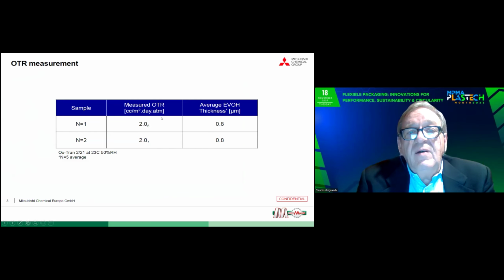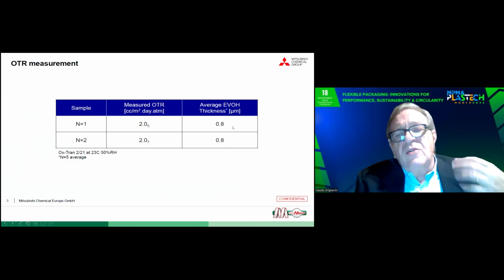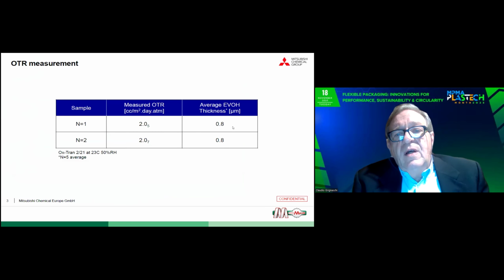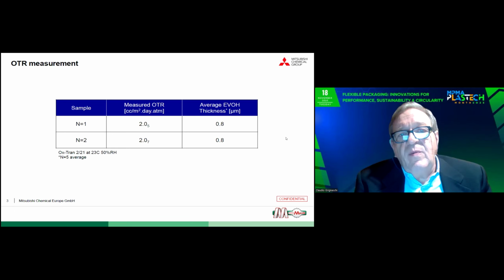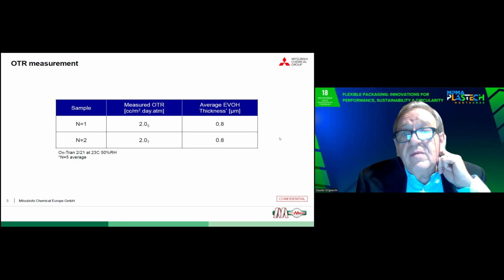This was the measurement of the OTR, given the average EVOH thickness. So a line able to guarantee you the oxygen transmission rate that you desire at a very low thickness. What is important is not so much the 1 micron, which shows the precision and legendary quality of the mechanical processing of Macchi—all die heads are designed and manufactured in-house on our tooling machines—but that we were able to constantly keep the EVOH layer as low as a maximum of 4% of the overall structure, producing a film which can be considered monomaterial and therefore fully recyclable.